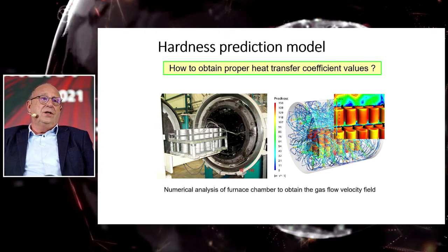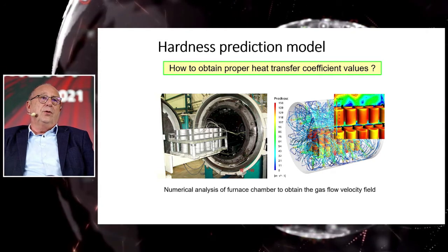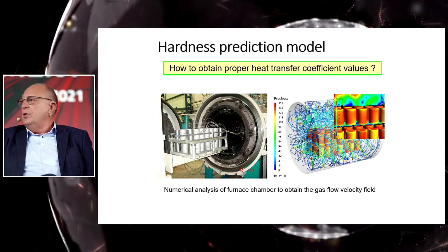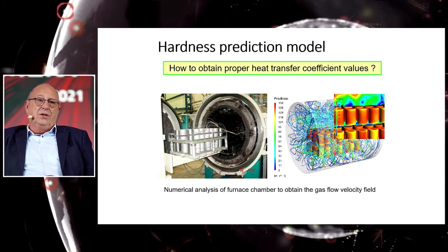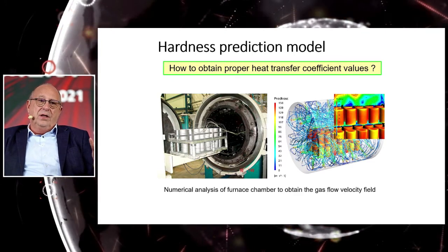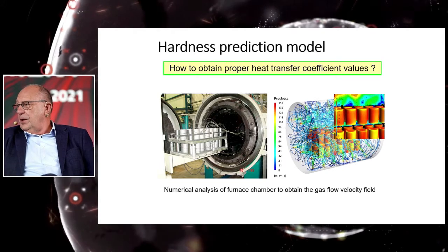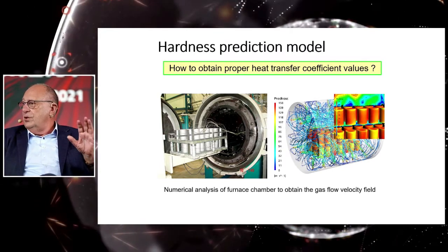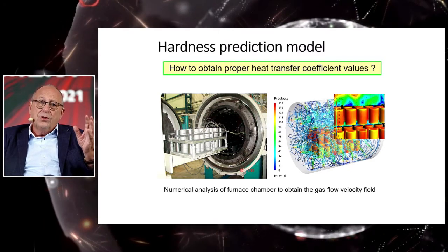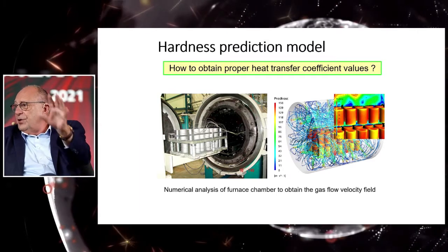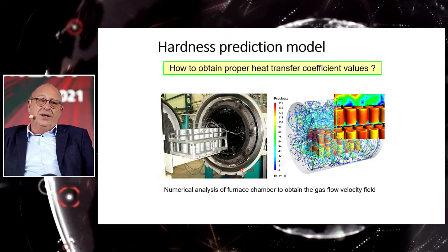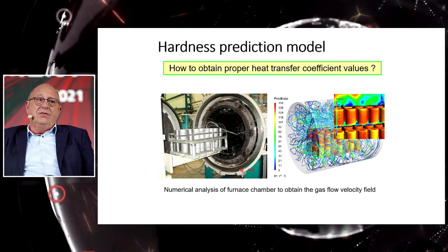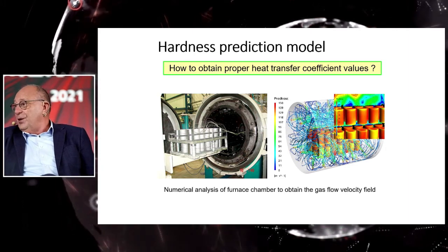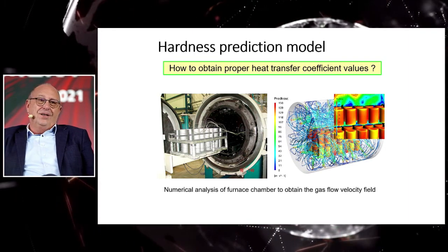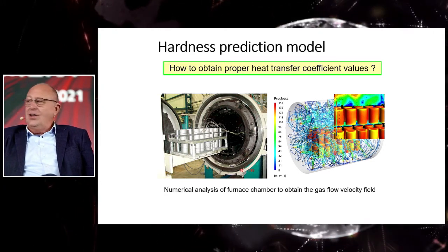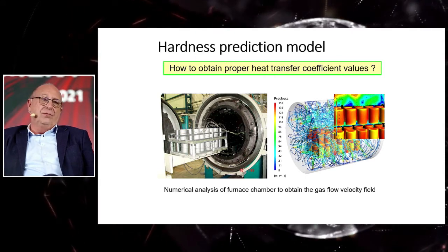The first and very important was to obtain the proper heat transfer coefficient values in high pressure gas quenches furnaces. The first approach we did using the conventional computer fluid dynamics programs. So the first approach was the estimation of the chilling rate and heat transfer coefficient for the dedicated furnaces at dedicated pressures of inert gas, and then all this data have been confirmed by numerous experiments. So we are really very sure that this data describe very well the real phenomena inside of vacuum chamber.